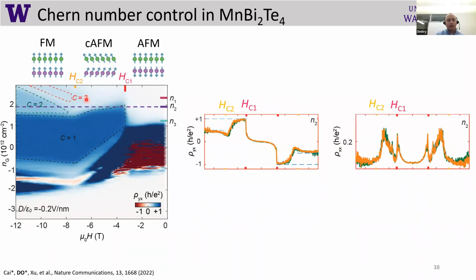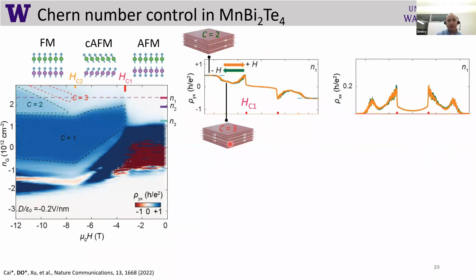If we make a line cut here, we would see something a little bit unusual again, which is that when we increase magnetic field, we first get Chern number 1 and then Chern number 2, as shown with these dashed lines. So this is contrary to usual quantum Hall effect, where you would see the opposite. You would see first higher Chern numbers, and then you would get to Chern number 1 at high magnetic field. That's not the case here, and I'll explain more about it in the following slides. And then the third line cut, for example, cuts through Chern number 3, Chern number 2. This looks more like usual quantum Hall state.